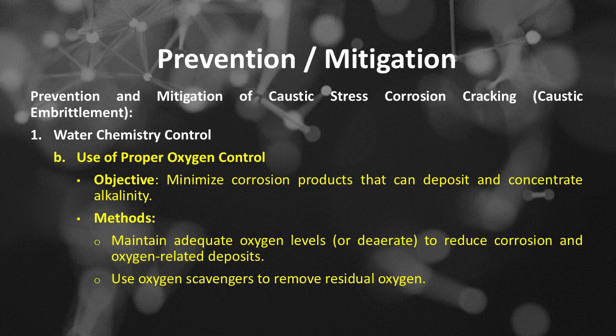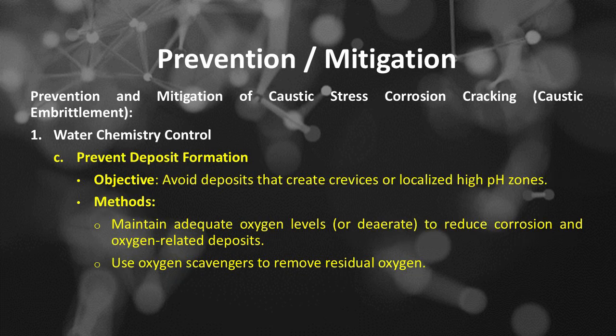Methods in use of proper oxygen control include: maintain adequate oxygen levels, or deaerate, to reduce corrosion and oxygen-related deposits, use oxygen scavengers to remove residual oxygen. Number C of water chemistry control is prevent deposit formation. Its objective is to avoid deposits that create crevices or localized high pH zones.